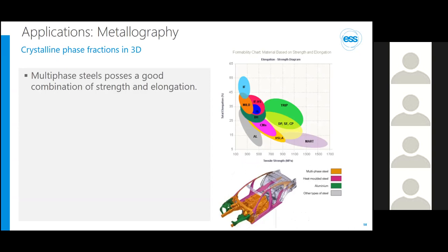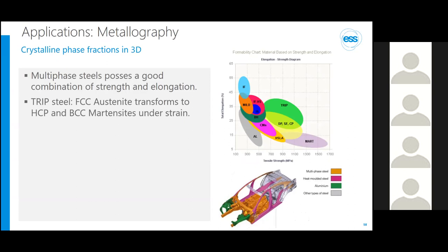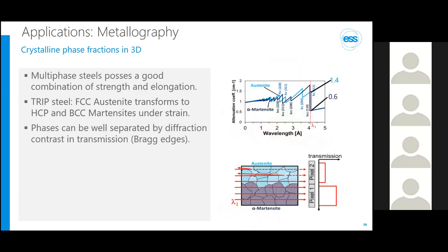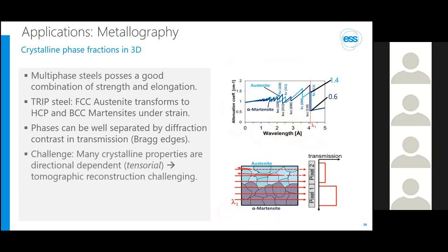Now coming to an example application where we investigated a multi-phase steel that has a good combination of strength and elongation. We used a metastable austenitic stainless steel that exhibits a so-called transformation-induced plasticity, or TRIP effect. It is widely used because of its good formability. Austenite and martensite are the two phases, and they can be well separated in the neutron transmission spectrum due to well separated and strong Bragg edges that you can see here.